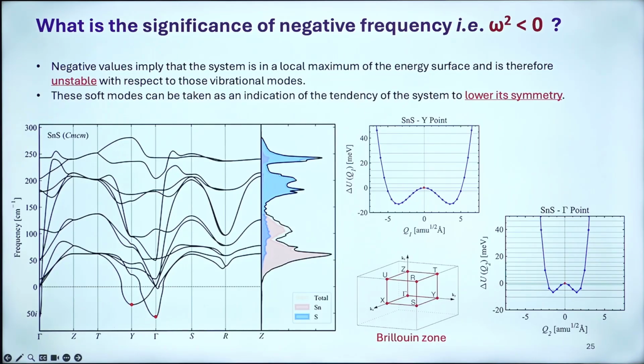and we don't see any kind of polarization. We are doing density functional perturbation theory, which computes the phonon frequencies within the harmonic approximation. This has to be taken with a pinch of salt. If there is anharmonicity, then also you will get imaginary phonon frequencies. But one has to be very careful whether it is purely coming from the ferroelectric point of view or whether the system has large anharmonicity.